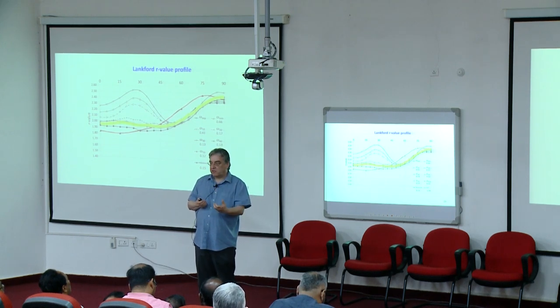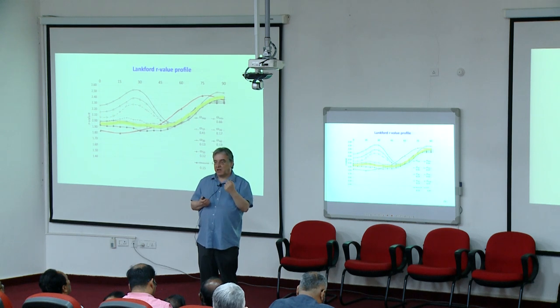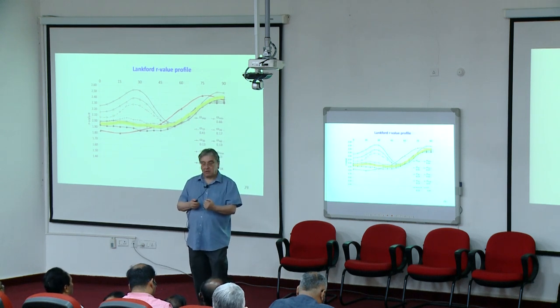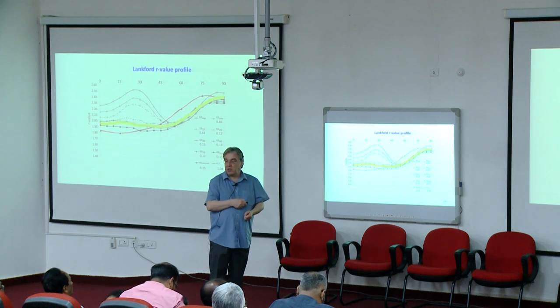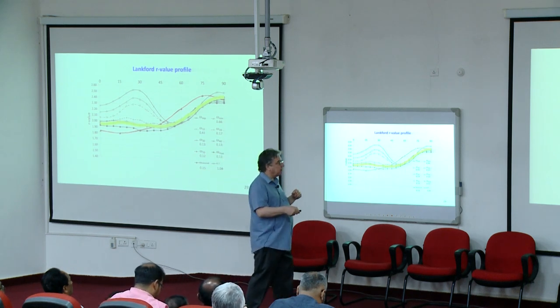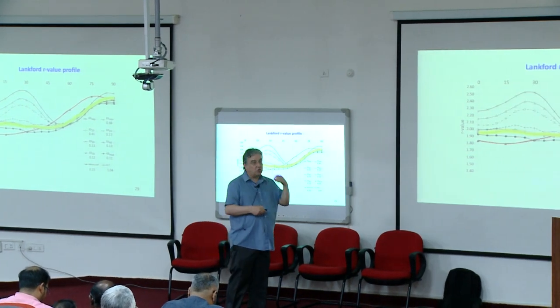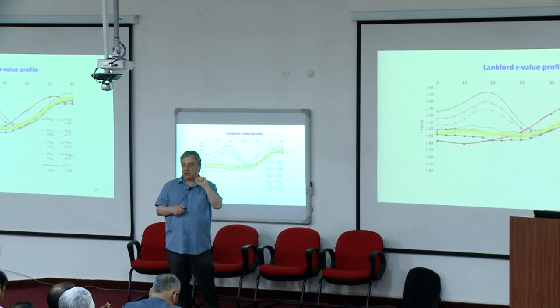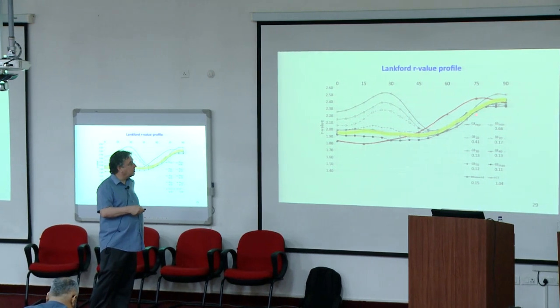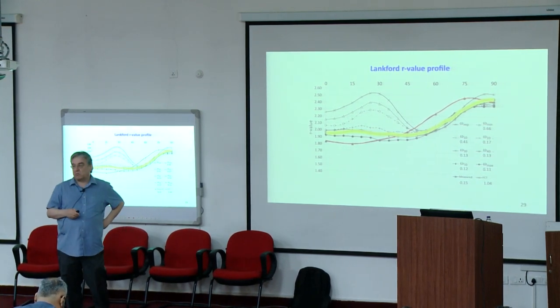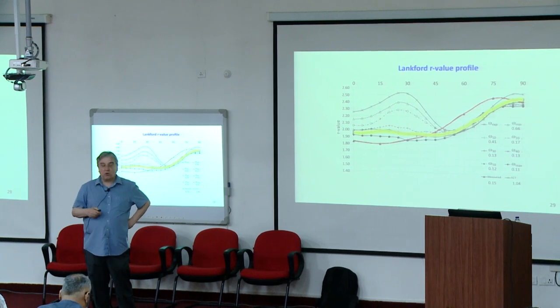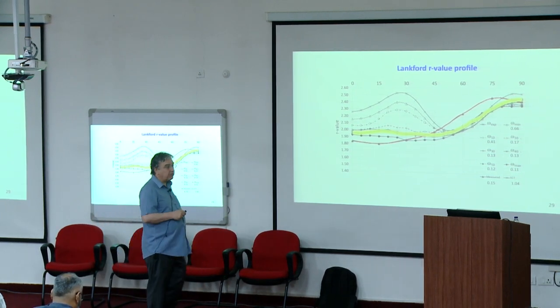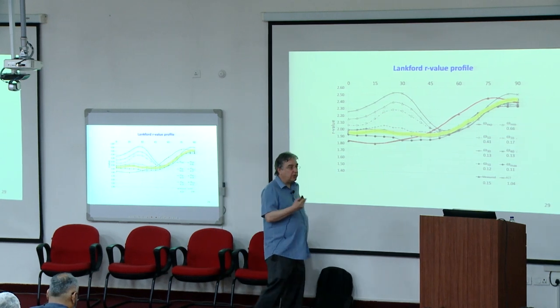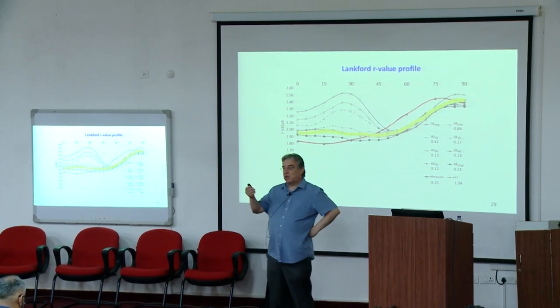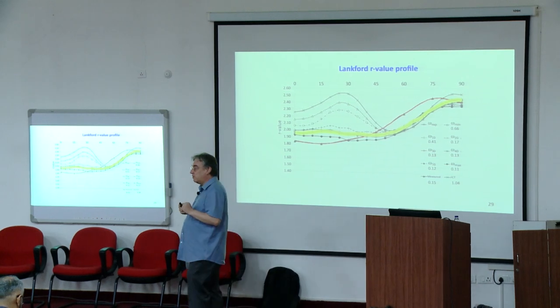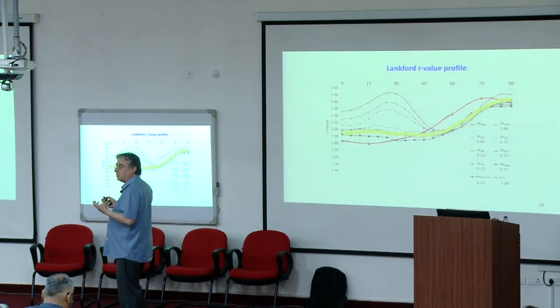One of the challenges is that aluminum is much less deep drawable than steel, and you can see this exactly with the R values. Coming back to my story, even if you have the true topology that we put in our ALAMEL model, the result of our simulations of the R values are not that much better. So actually, it shows that to some extent, the R value is a mechanical property that is not really sensitive, between certain limits, to the topology of the microstructure.